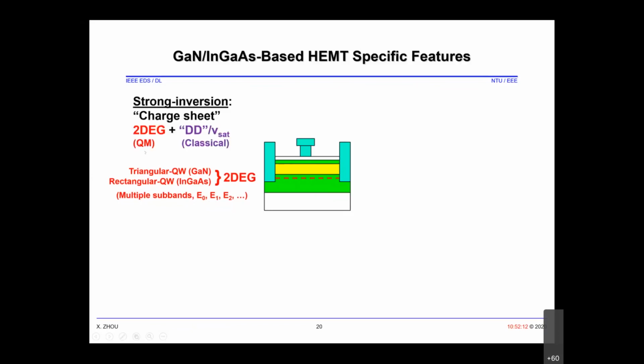this you can see the sheet of 2DEG is similar to the charge sheet model in the conventional silicon model. So we are based on the drift-diffusion with velocity saturation model, but we're including these quantum effects from the 2DEG. We have also included a moderate inversion where the Fermi level is below the bottom of the subband, but still positive. So this is the so-called moderate inversion region.